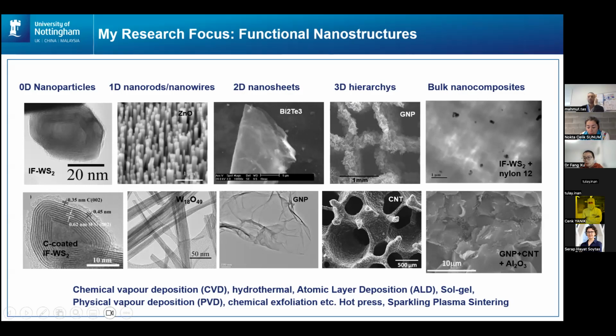We also work on reinforced nylon 12, and graphene oxide and carbon nanotube reinforced alumina ceramic composites. The technology we are using includes chemical vapor deposition - this is how we grew our carbon nanotubes on ceramic foam; hydrothermal methods, which we use to grow our tungsten oxide nanowires; atomic layer deposition, how we grow those very ordered zinc oxide structures; and sol-gel, physical vapor deposition, and chemical exfoliation.